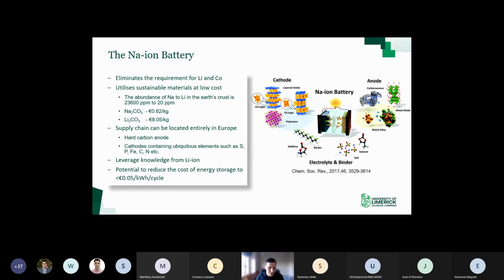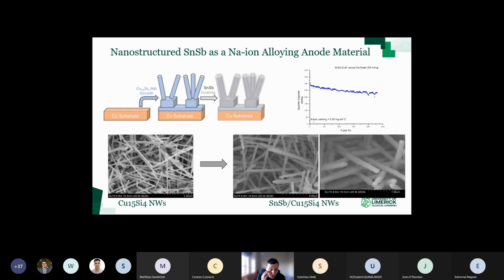Because of the cost reduction, you have the potential to reduce the cost of energy storage to less than 5 cents per kilowatt-hour per cycle, which is a key target of the EU. What we are doing now, and this is not part of the Trident project, this is a separate SEAI project, is research that Stephen O'Sullivan is doing. He's looking at alloying materials rather than hard carbon as the anode. Stephen is taking the copper current collector and growing inactive copper silicide nanowires. Basically they act as a current collector, but a high surface area current collector.